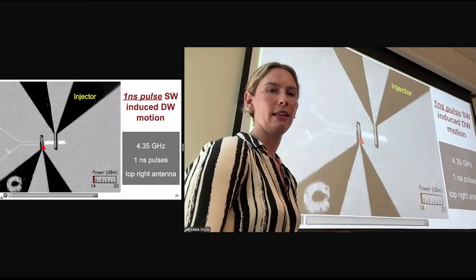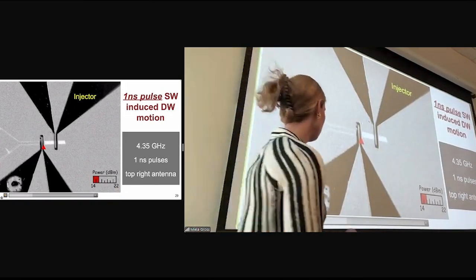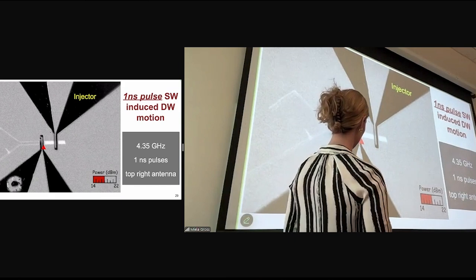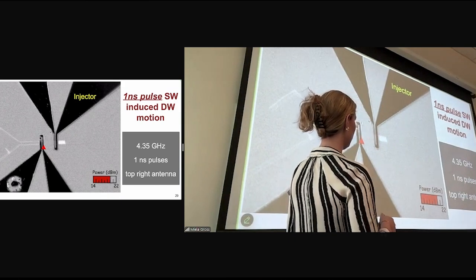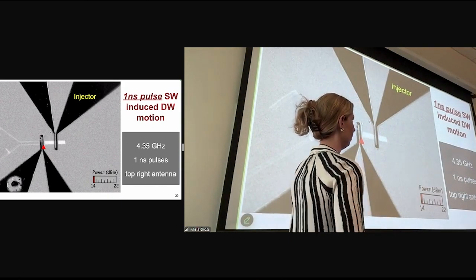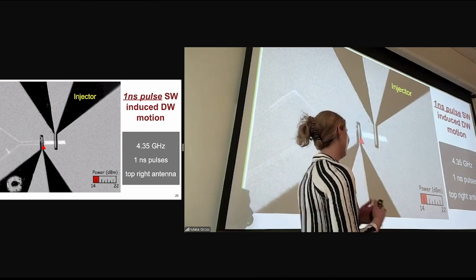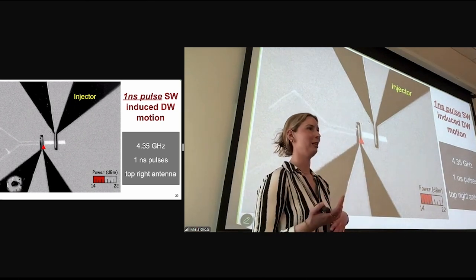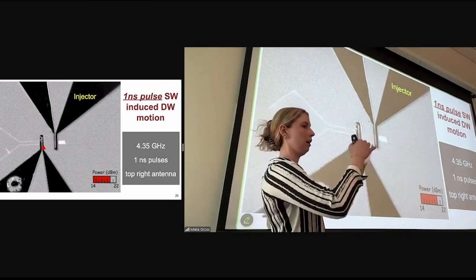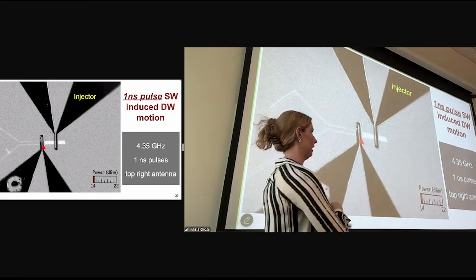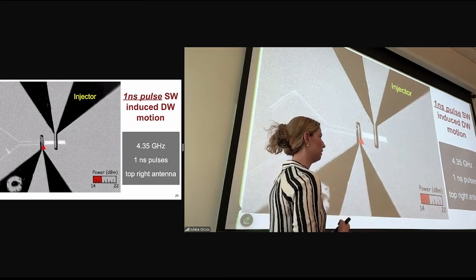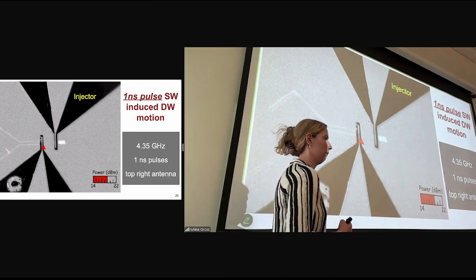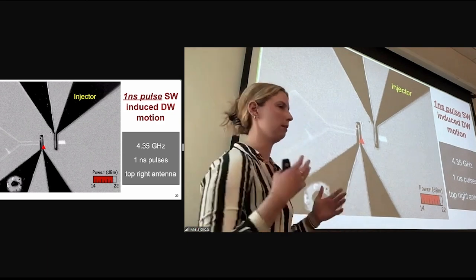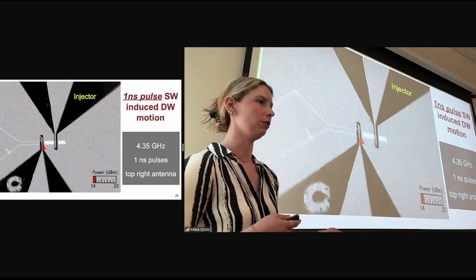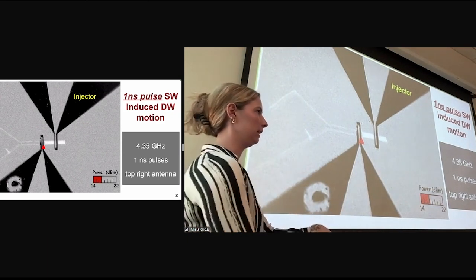We see that the domain wall moves an entire 15 microns between these two antennas, under the injector antenna, which is pretty awesome. When we consider the power loss from the RF pulse to spin wave excitation and then the decay length of the spin waves, we calculate the actual energy of the spin waves to be just 4 picojoules, propagating the domain wall 15 microns.